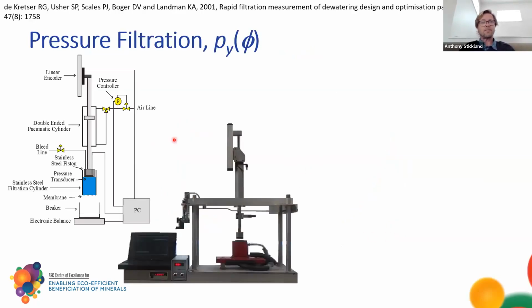For pressure filtration tests, there's a range of different devices available to do this. This is what we've got, which is a bespoke filtration device. In particular, we've got a pressure transducer mounted in the face of the piston that allows us to ignore frictional losses of the piston. So we can directly measure the pressure that we're applying to that cake. We can measure the displacement from a linear encoder, so highly accurate measurements there, and it's all controlled with a PC.